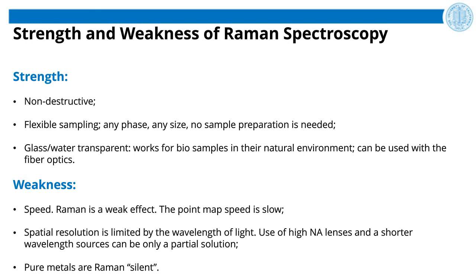Well, we can add to this that the intensity of the Raman response for particular compounds depends on the excitation wavelength of the laser used. That means that to get a Raman response from a particular compound, we need to use a specific excitation. There is a general trend that organic materials have a strong response when red or infrared laser excitation is used, whereas inorganic materials have a better response with green or blue lasers. That means that for a given Raman system, you are not guaranteed that you always get a proper response. Sometimes you have to check your materials using different excitations to find which one works best, and it means that specific types of studies on different materials require different types of excitation, and you are lucky if you have all these capabilities in one system.